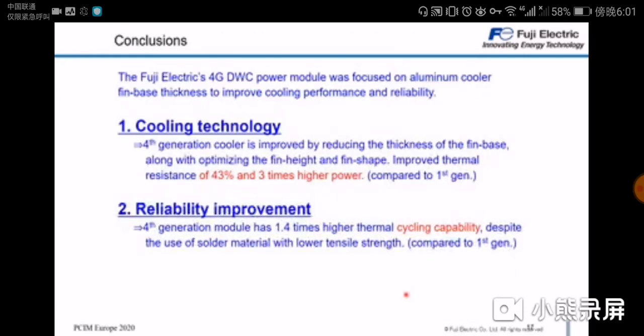Now we come to our conclusion. The main focus on our 4th generation water cooler was to increase the cooling technology itself by reducing the fin-base thickness and optimizing the fin height and shape to have the perfect trade-off between thermal resistance and pressure drop. We were able to decrease the thermal resistance by 43% and at the same time increase the power density by a factor of 3 compared to the 1st generation of water coolers.